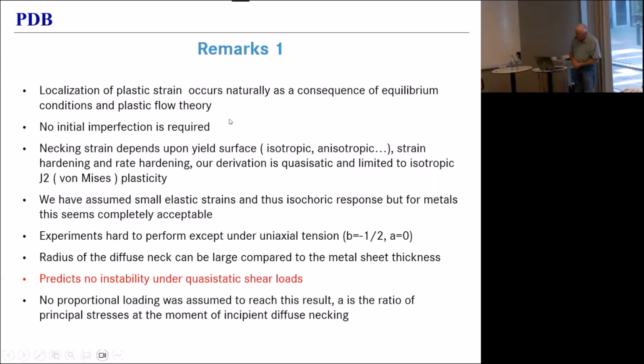I have a bunch of remarks. I'm not sure I want to go through all of them, but maybe of this entire page, the only one important is the one in red. It's that this method indeed predicts no instability under quasi-static shear loads. That doesn't mean, of course, that it never happens. We have no temperature effect here. If we would include thermal softening, you would very, very naturally get an onset of localization under pure shear. And that would be an adiabatic shear band. But we didn't include that here.